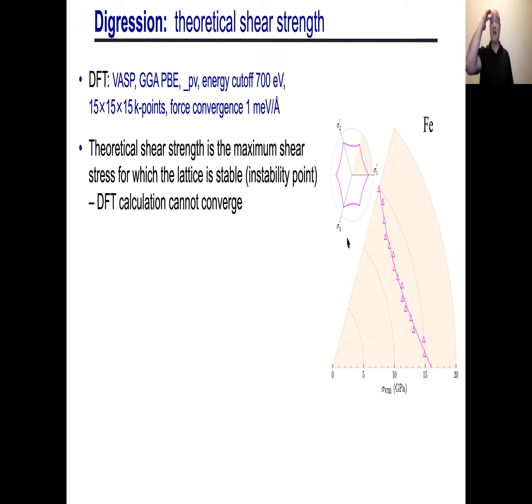Okay, so what is the theoretical strength of the material? If I take a crystal and I apply a shear stress, at some stress I can no longer maintain that stress value. Strain will just go to infinity, which is to say the DFT calculation cannot converge at that stress level. So this is a mechanical instability, okay? So I can do this. A few other people have done this with DFT. There's a group in Czech Republic that's looked at this. A few other groups have looked at it.